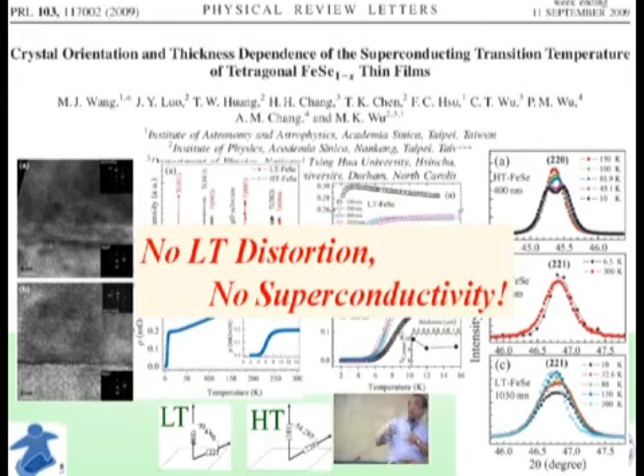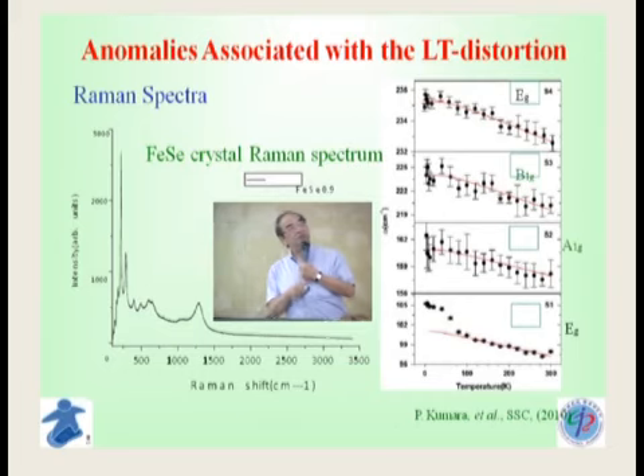And then we have to ask, why is there this distortion, and what does this distortion lead to? This is what we are currently working on, trying to understand from the physical properties to get a better understanding of what's going on. We have done a lot of work. This just quickly shows you some of the data, like the Raman. There is probably some phonon mode that has changed at that temperature because of the distortion. And this is understandable because the structure is different at lower temperature.